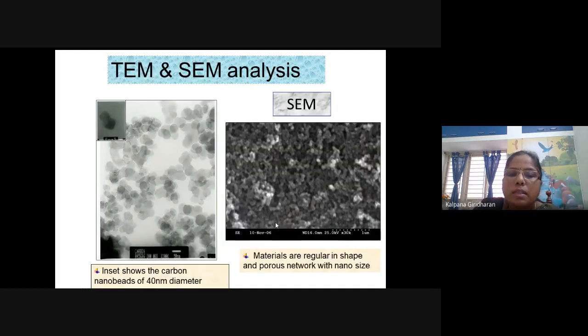This is the SEM analysis. On the right side, this shows these materials are very regular in shape, with a good network and porosity. This is the bead I mentioned - it is typically a bead kind of structure, of 40 nanometer size.